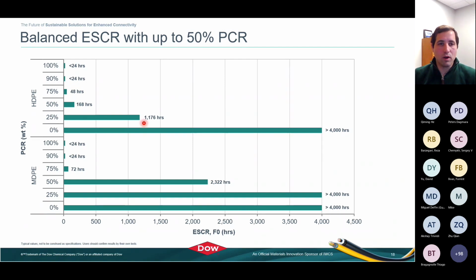1,000 hours or more with 25% in high density, which tends to have a bit lower ESCR depending on the material. That medium density even over 2,000 hours, in this case with the higher performance starting resins, where 50% loading gets you that 2,000, and then even lower you can still reach the 4,000 hours.